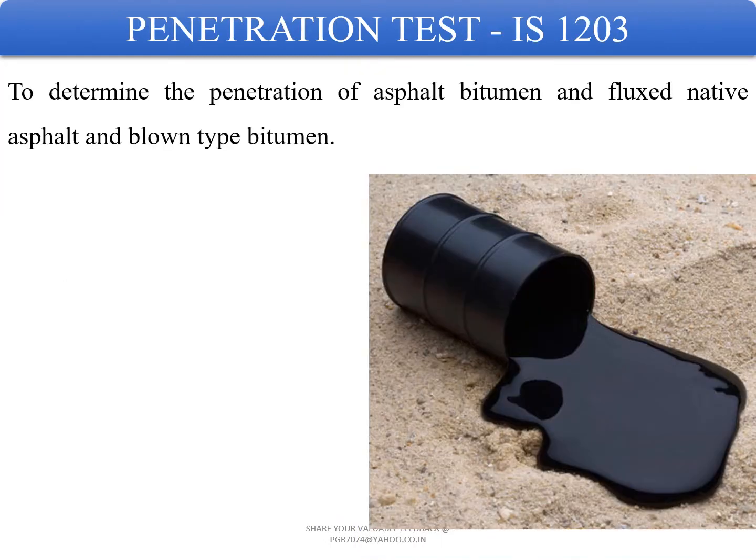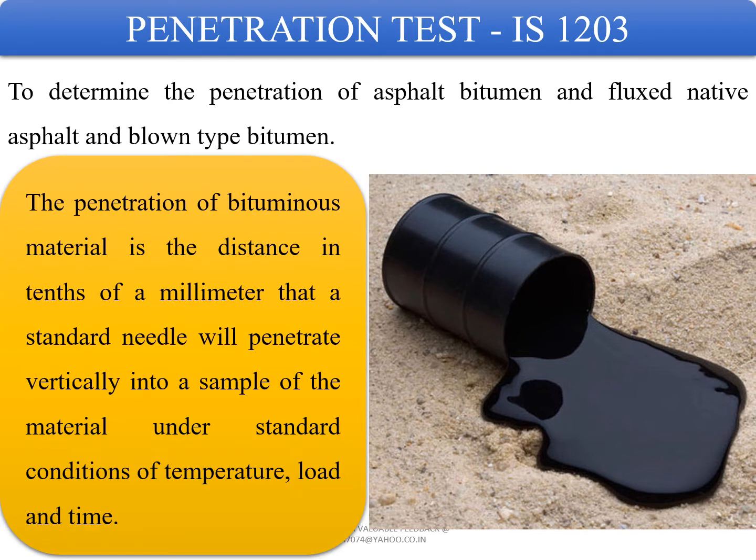The penetration test is conducted as per IS 1203. The objective of the test is to determine the penetration of asphalt bitumen, fluxed native asphalt and blown type bitumens. The penetration of bituminous material is the distance in tenths of a millimeter that a standard needle will penetrate vertically into a sample of the material under standard conditions of temperature, loading, and time.